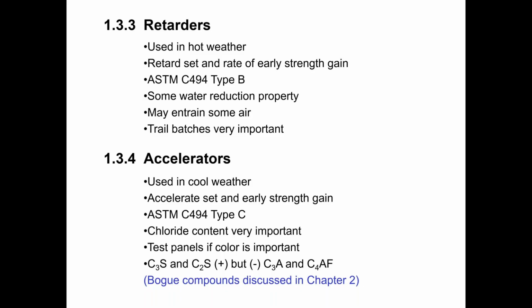Retarders may also entrain some air. So some trial batching probably needs to be done because you can quite possibly reduce the amount of air entraining admixture that you're using if you start incorporating a retarder into a mix. But trial batching is recommended so that you can evaluate what those effects are with your particular mix design.